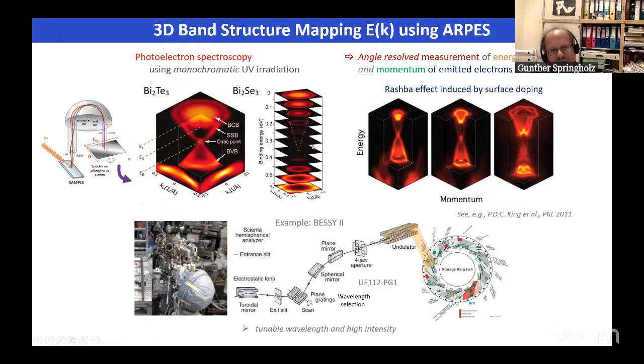So in this way, one can make these beautiful three-dimensional maps of the electronic band structure of various materials. Here, an example for topological insulators, bismuth telluride and bismuth selenide. And here on the right-hand side, you also see the appearance of the Rashba effect on the surface of bismuth selenide induced by surface doping, where you see the emergence of this Rashba splitting in the system.